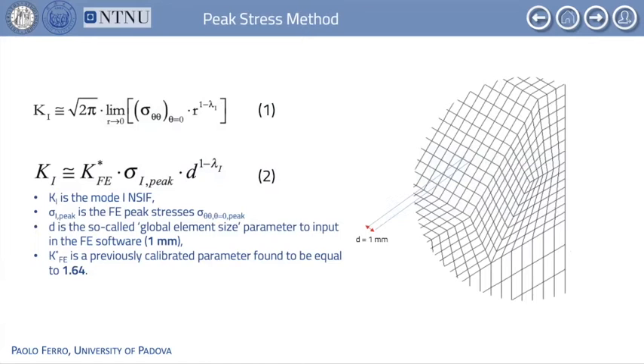In local approaches, the weld toe is schematized, referring to the worst case, as a sharp V-notch with zero tip radius, inducing an asymptotic stress field whose intensity is quantified by the notch stress intensity factor K1, given by Gross and Mendelson's definition in 1972 and described by equation 1 in this slide.